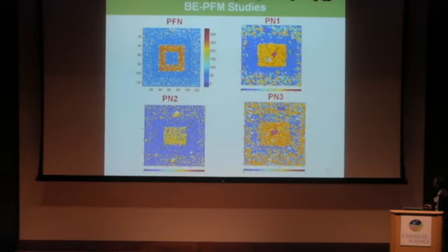So in order to confirm the ferroelectric nature of all the thin films, we have studied some band excitation PFM measurements. Here we have poled the sample with positive and negative 5 volts. We can see the phase contrast in positive and negative areas.